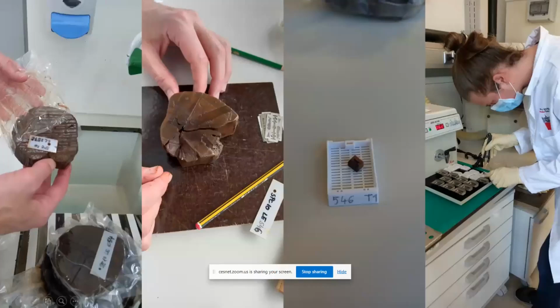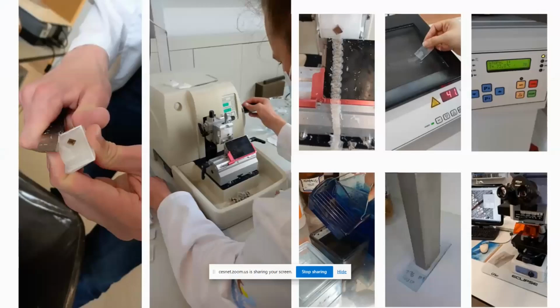Here you see that we store those samples in a refrigerator, under vacuum and waterlogged. Then, to make slides for light microscopy, we prepare the sample before cutting it into a small oriented sample, and then we embed it in paraffin. In this way, it becomes harder and easier to cut. Then we prepare the paraffin block, and we obtain a slide of 9 micron thickness.